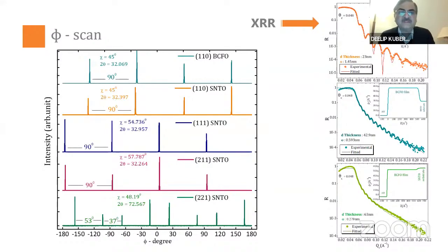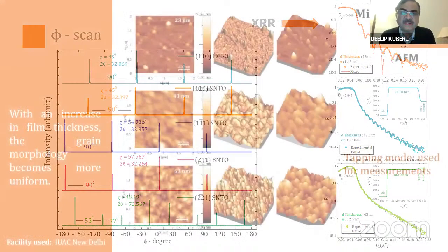And once you know this, then you can do phi scan measurements, and then you can do the X-ray reflectivity (XRR) measurements also. You can set up your setup for the X-ray reflectivity, and from the fringes and from the calculations, you can find out the thickness of the films also. The thickness of the films was found out from the X-ray reflectivity measurements.